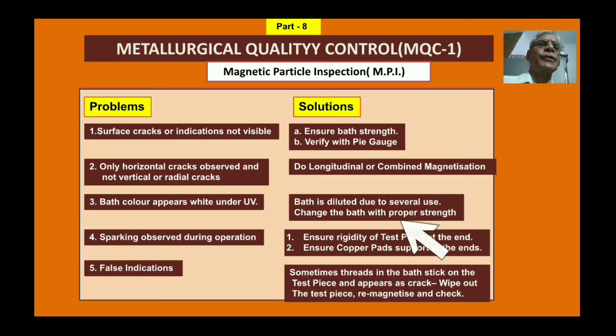Now, what are the problems being observed and what are their solutions? The first one is that the surface cracks or indications are not visible. It happens sometimes that you are not finding it. In that case, you have to ensure that the bath strength is okay, whatever bath you have made, and then verify with the pie gauge whether cracks are visible or not. If you check again and something is wrong, then you have to make a fresh bath, check the current requirement also, and then check again. This is one of the solutions for this particular problem.